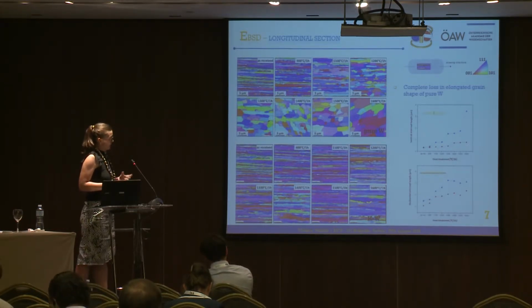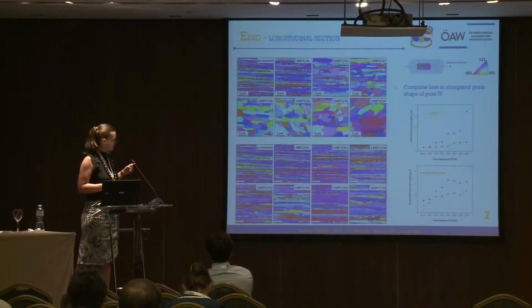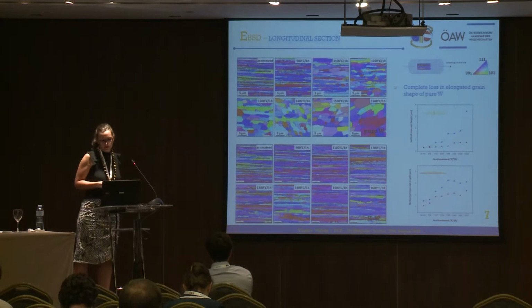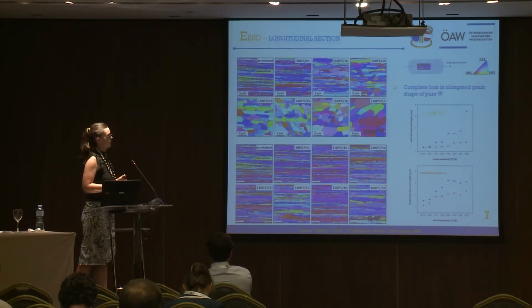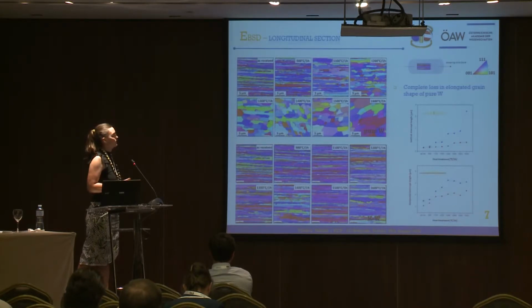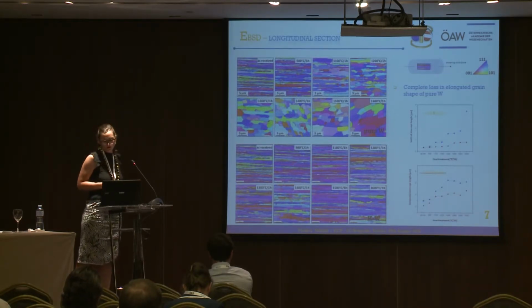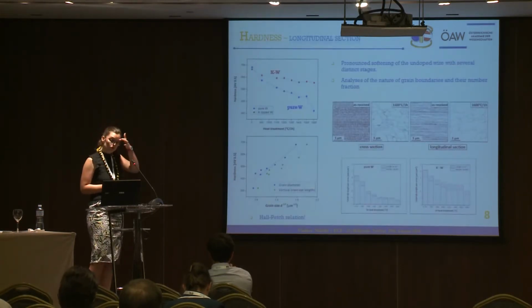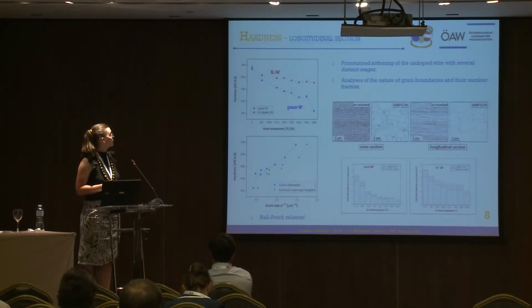Some grain width increases a bit above 1400 degrees C, but nevertheless, the elongated structure is still preserved in this case. And here, accordingly, we can see the changes in grain length and width. And then two additional pieces of information we collected.